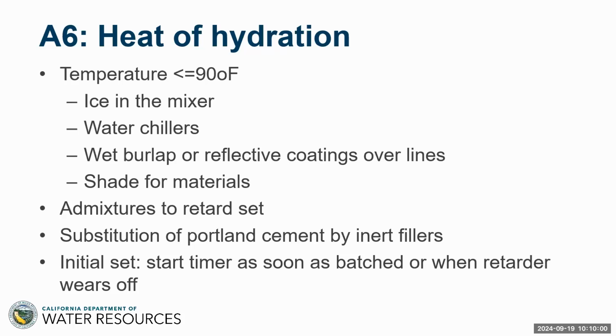Many of the guidances that we have for processes like micropiles and anchors say that the grout temperature should never be more than 90 degrees Fahrenheit. How do we ensure that if we're working in the desert or we're working down in Florida or something like that? Classic defenses that the contractors are using is putting ice in the mixer, using water chillers, wrapping the exposed lines in wet burlap or reflective coatings, just to try and keep the heat away from the grout in the lines. And then always putting the cement and the bentonite and any sand in shady conditions, because these are the biggest components, as we said before, of the grout. And therefore, if we can minimize the heat absorption, that is very helpful.